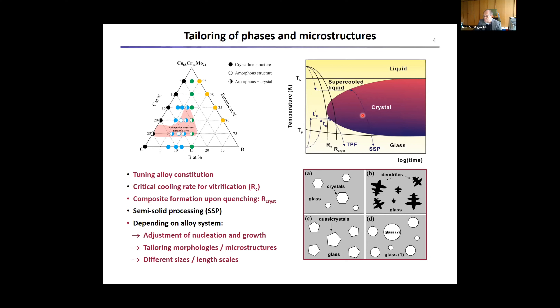Just schematically shown here, you can have an amorphous matrix with crystals of different size and shape — can be dendritic, primary crystals, or eutectic phases, depending on the exact composition. It could even be something more exotic like phase-separating systems where you have a microstructure comprised of two different amorphous phases that coexist. What I would like to do in the next slides is to guide you through this phase space and show what you can get and how you can tune the mechanical properties.